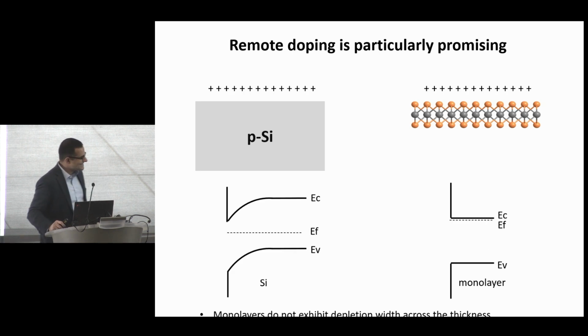Now what I can do is place a sheet of charge, fixed charge, somewhere close to the semiconductor. And if you can somehow put a slab of fixed charge in close proximity to your conventional silicon, of course, you end up getting energy band bending. And this is how, of course, a MOS capacitor works. The slab of charge is created by a gate. But this concept can also be used for VT control, the threshold voltage control. And this concept is also used in most commercial silicon solar cells. In silicon solar cells, they create surface band bending by putting, for example, insulators with fixed charges in them in order to repel the minority carriers from the surface.